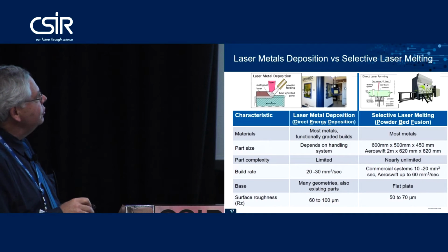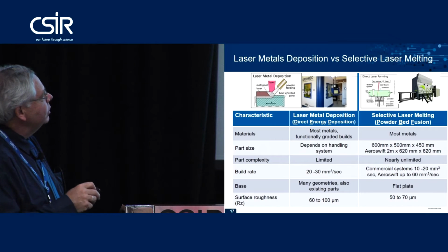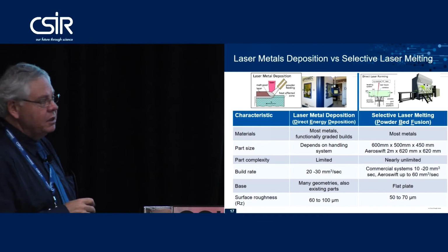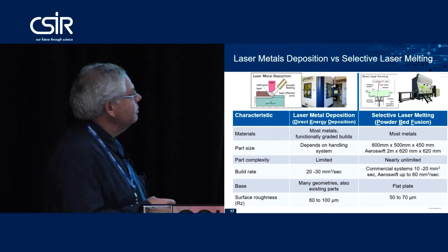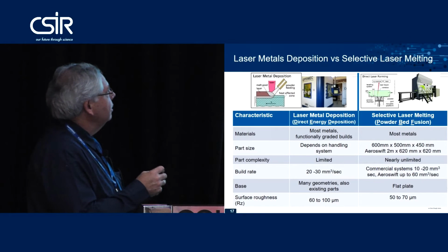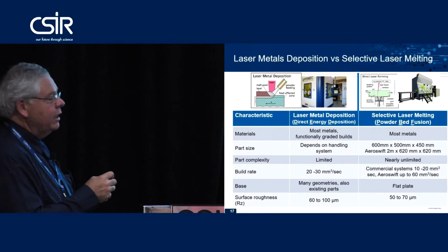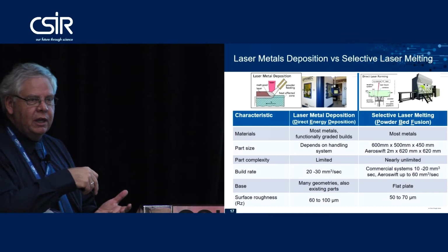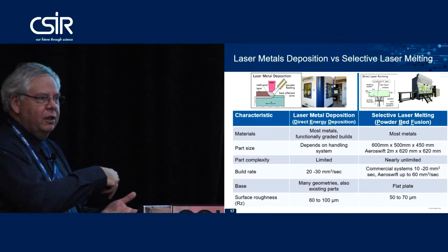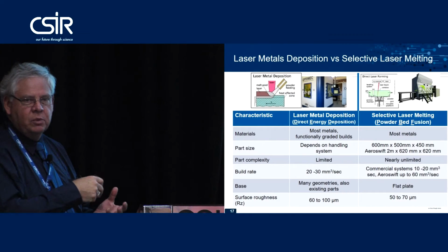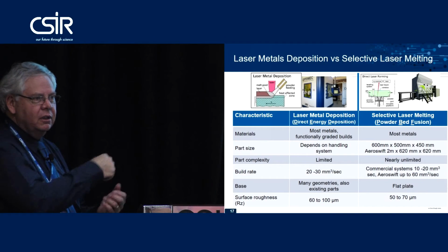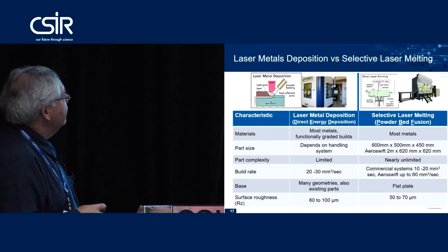So this is powder bed fusion, compared to what we call laser metals deposition or direct energy deposition, which is the correct ASTM term, where we actually blow metal powder into a laser beam, and wherever you move the laser beam and the laser powder nozzle, you deposit a weld bead, and in this way you can also build up or print a component.